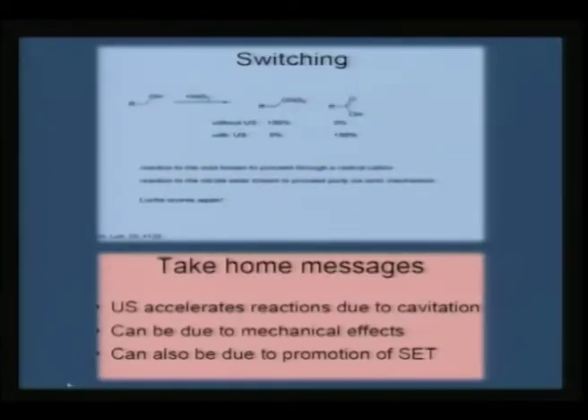And if you look at the switching reaction, for example, if you try the conversion of this alcohol using nitric acid with ultrasound, you see complete conversion to this switching form, whereas without ultrasound you almost see 0% conversion. Without ultrasound this is not possible, whereas with ultrasound this is possible. Therefore, the reaction with the acid is known to proceed through a radical cation reaction, the reaction with the nitrate ester is known to proceed purely via anionic mechanism.